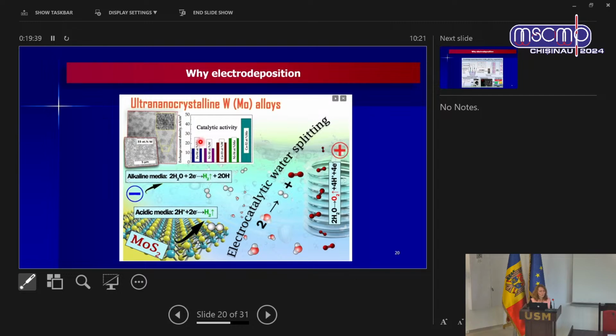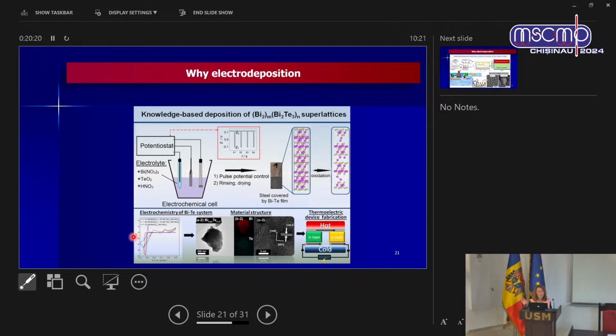And the catalytic activity of these ultra nanocrystalline coatings, alloys, in this case, is very high and applicable, for example, for electrocatalysis, also water splitting. Also our group developed materials based on molybdenum sulfide, and titanium oxide was mentioned yesterday. So we have a lot of work in electrochemical materials. Also, with our colleagues from Belarus, we developed knowledge-based deposition of very nice superlattices, which can be used for thermoelectric device fabrication. Why is it knowledge-based? Because they wisely used pulse deposition techniques to create a very nicely developed structure of these superlattices. Also good results, you can find more in our publications.